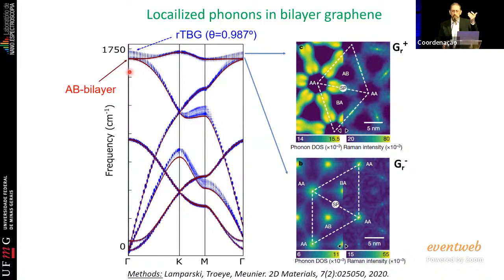We saw a little bit of this when I showed the imaging of this phonon dispersion relation by rotating graphene. But here the angle is very small, so this generates a high density of states here. And with atomistic calculations, what I call atomistic calculations is when you model electrons and phonons in these systems, you cannot rely on the periodicity of the unit cell. You have to really account for every atom movement, on thousands or millions of atoms. And when you do this, you can look at the vibration or electronic structure locally.